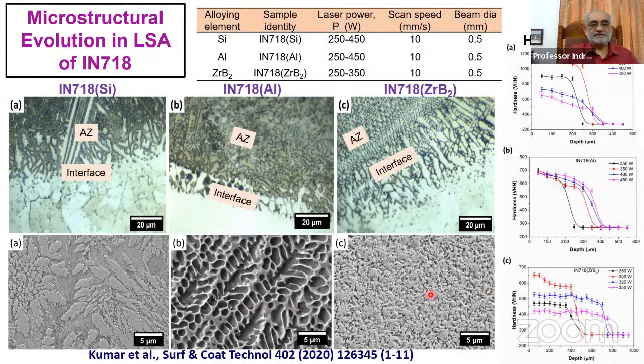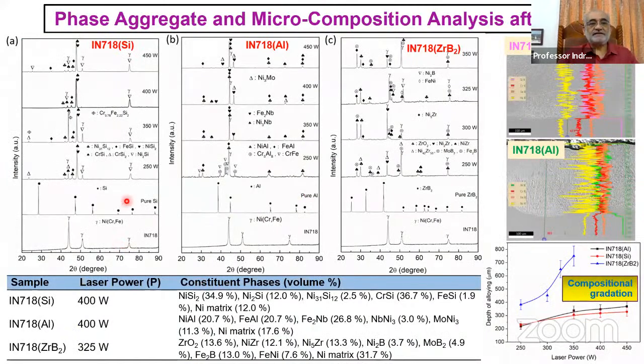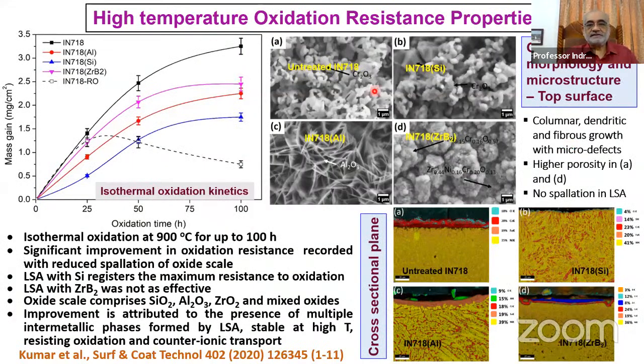Whereas from the top surface, this is the kind of microstructure you develop. So this basically is very useful. This is the hardness profile, and this is all the diffraction evidence about the phase aggregate and their identity and distribution. And this is the microcompositional profile to show that there is indeed compositional gradation. And this is the evidence of the oxidation resistance.